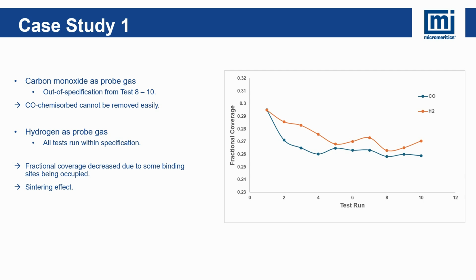Comparing carbon monoxide and hydrogen probe gases, the dispersion value of carbon monoxide continuously decreased and eventually fell out of specification. The reason being that pulling a vacuum and applying heat was not sufficient to remove bound CO. The carbon monoxide molecule has a stronger binding affinity for metals than hydrogen molecules. In contrast, when hydrogen was used as a probe gas, the dispersion value decreased but remained within the specification. Therefore, using carbon monoxide as a probe gas could limit the number of times a catalyst can be used.